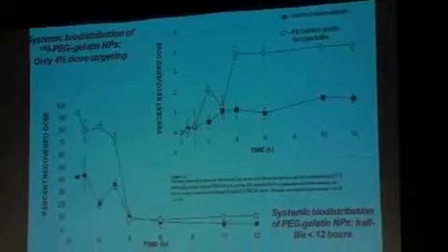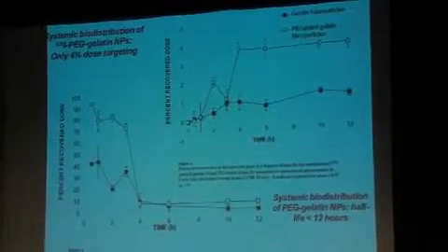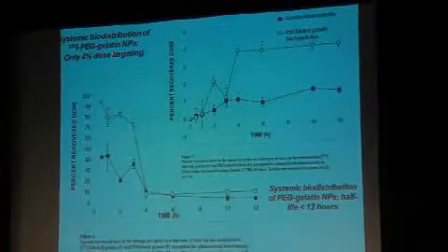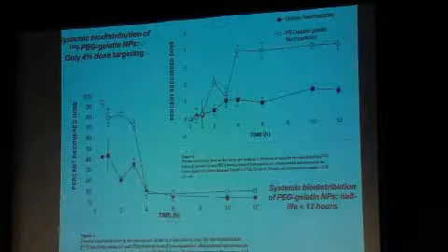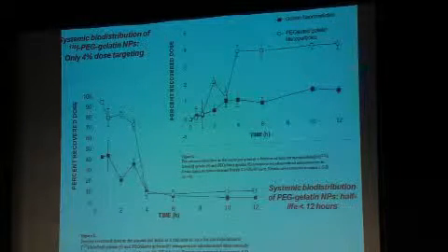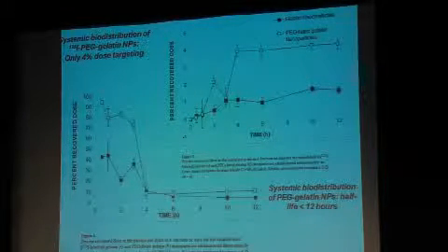All right, and here's gelatin. So this is a collagen analog. It's a biomaterial. It's approved for use in humans. And this time they labeled it with radio labels, and only 4% of the dose of these gelatin nanoparticles gets to the site of action. Most of it resides then in the liver and the spleen. So I don't know what else to say to bring that message home.